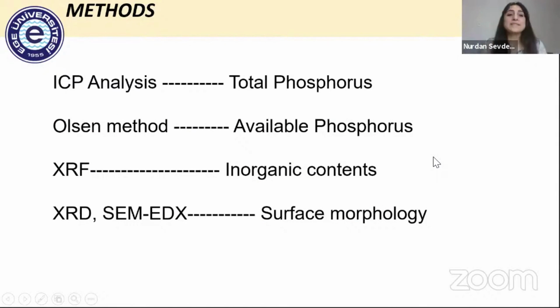In terms of analysis, we determined total phosphorus by ICP, available phosphorus determined by the Olsen method, and inorganic contents determined by XRF. For the surface morphology, we made analysis using XRD, SEM, and EDAX.